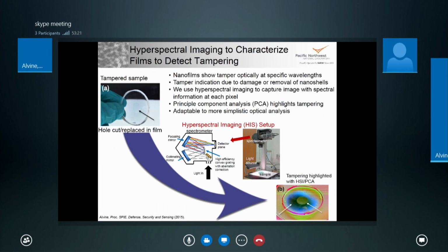So the main thing in this slide here is this is a nanoplasmonic film. It's encapsulated in an elastomer. And this center region, where you can see this very vaguely or barely see this circle, this central circle was cut and then rotated slightly. And so by eye, you can only barely tell that it was changed.